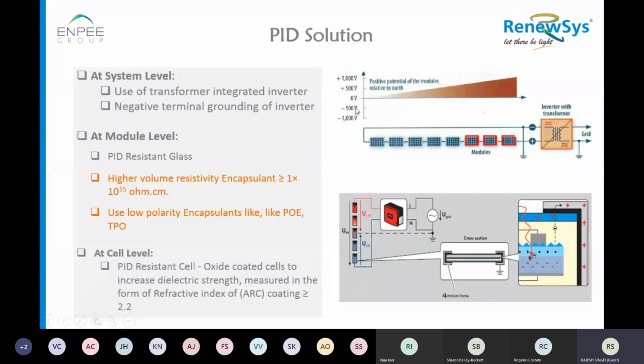Because PID is caused by the PV system at different levels, the solutions are also derived at different levels. So if I talk only about the module level problem, which is caused by low volume resistivity of the encapsulant, we can see here that an encapsulant of around 10 to the power 15 ohm centimeter is good enough to control PID caused by the encapsulant in the module.